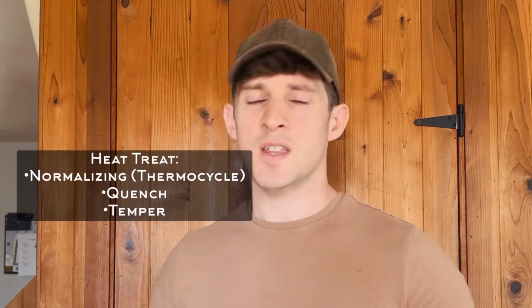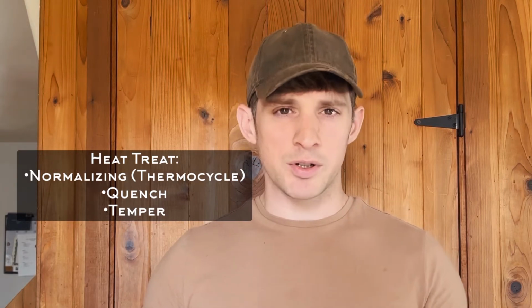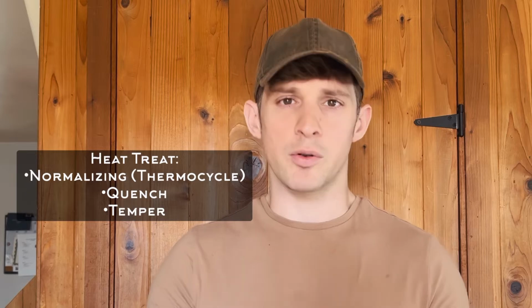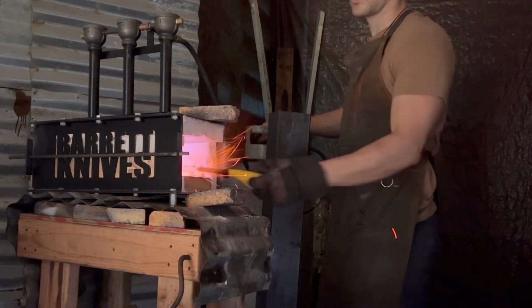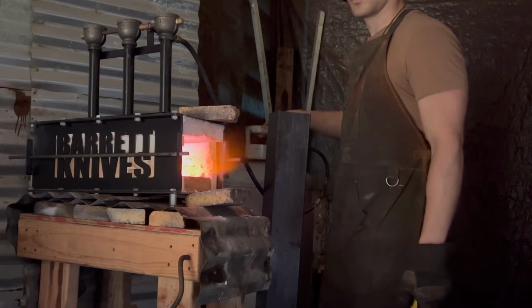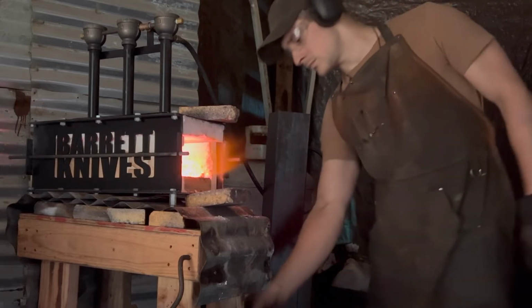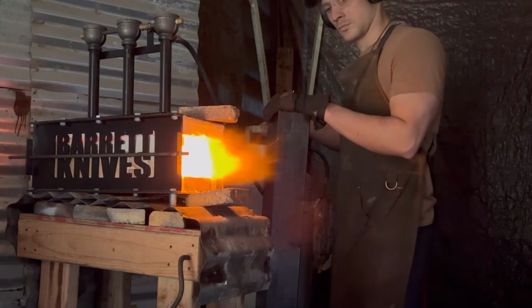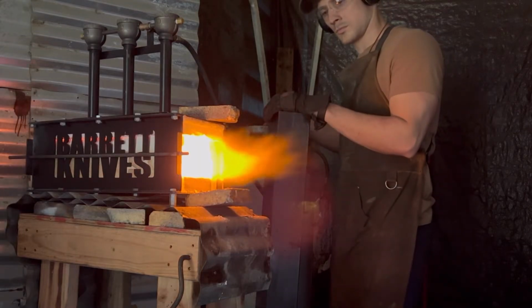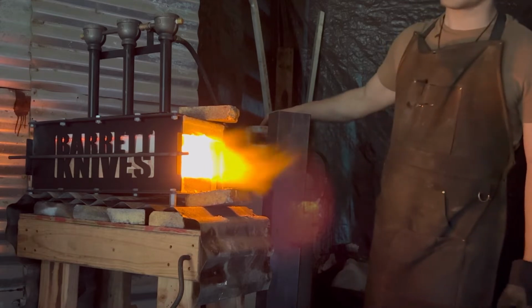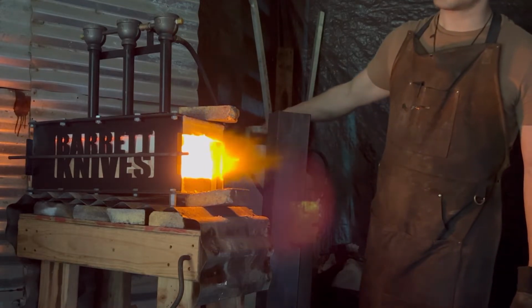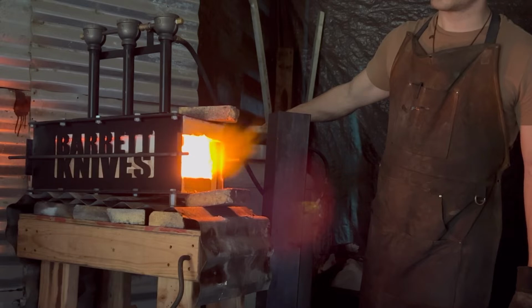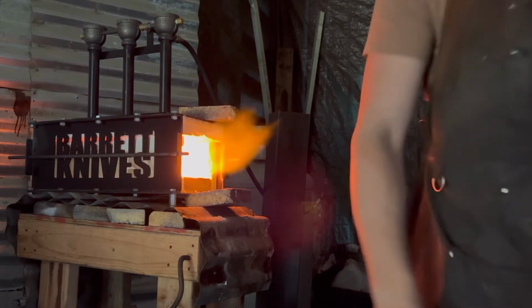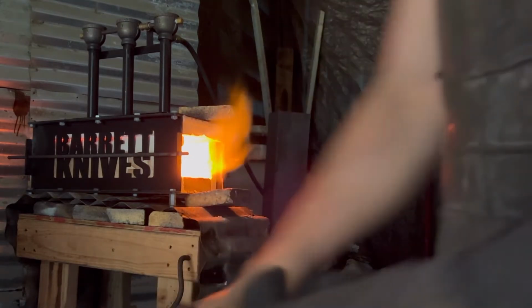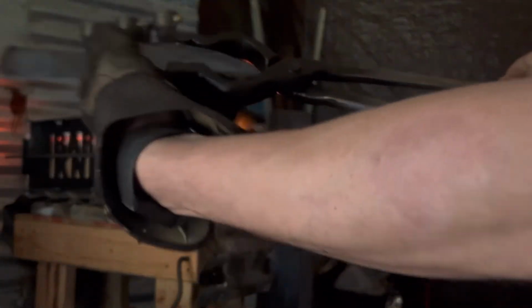So now let's talk about heat control for the heat treat. We've already talked a little bit about some of the heat treat procedure for a stock removal blade, but it's even more important when we are forging a blade. The reason is that because that steel is under the heat for so long while you're forging it, the grain structure inside that steel starts to expand and become very coarse. If you were to go straight from forging and then just dunk the steel into the oil, you could fracture it. It may actually break where you see a large crack, or it may just be a stress fracture where you don't even see it inside.